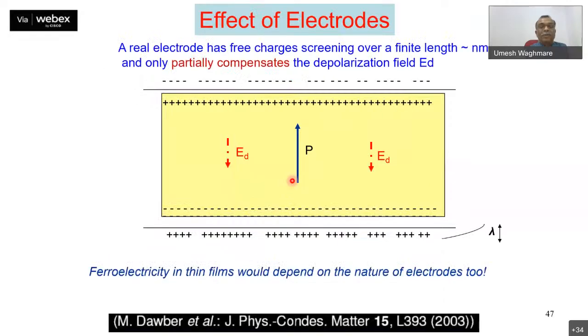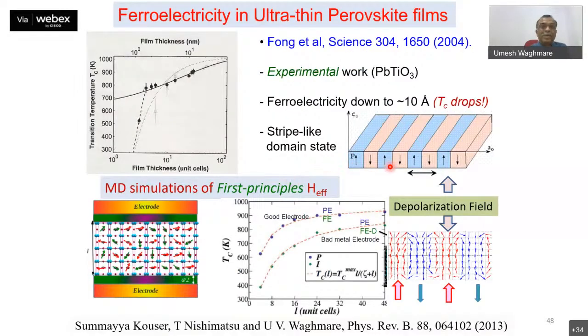And what is known from experiment, as well as theory from my group, is that at nanoscale, a ferroelectric actually decomposes into an inhomogeneously ordered state, a domain structure, where dipoles are up and down, up and down. This is called a stripe domain structure. And unfortunately, this cannot be used for the memory application that I talked about.